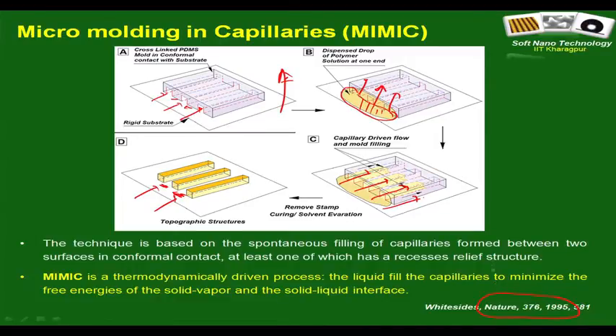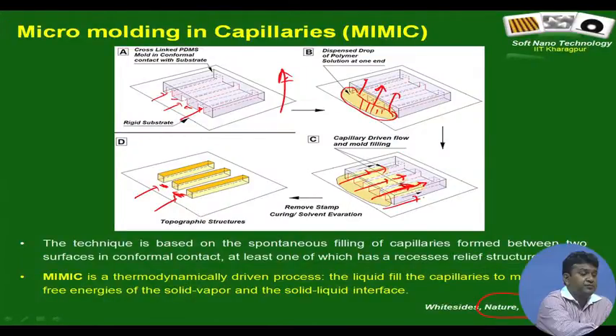There are, however, despite all the elegance of the technique, certain issues. One of the issues one needs to understand is that the capillary flow is with a dilute solution, and so eventually when the solvent evaporates away, you never get a structure with the polymeric material that corresponds to the full cross section, irrespective of whatever I have drawn. So, if this is the cross section of one channel, you are very likely to get some structure like this. Even this may or may not be there, this depends. This is sort of an indication that the stamp wall is wetted well, but you may not have this, and may have some shallow structures.